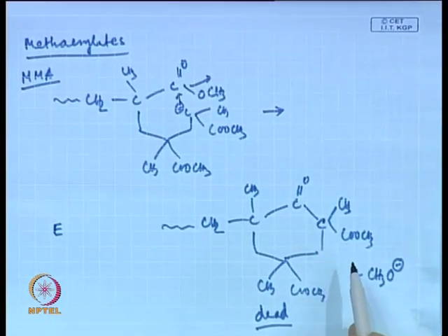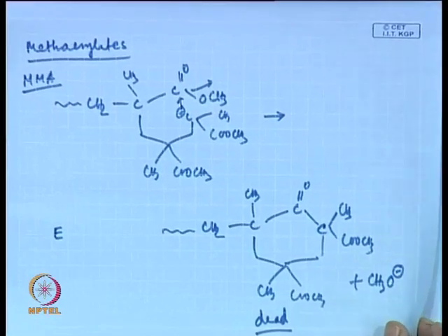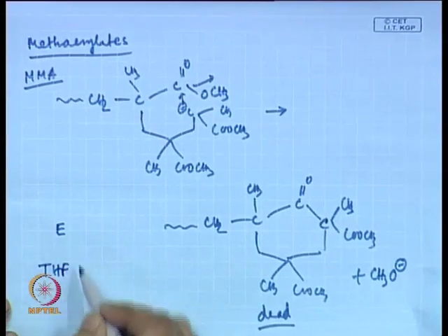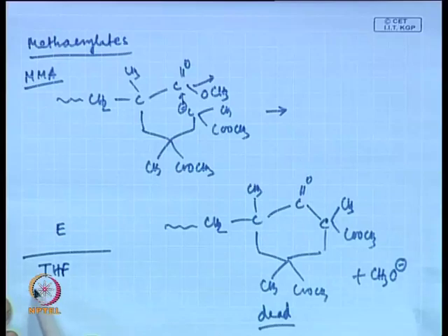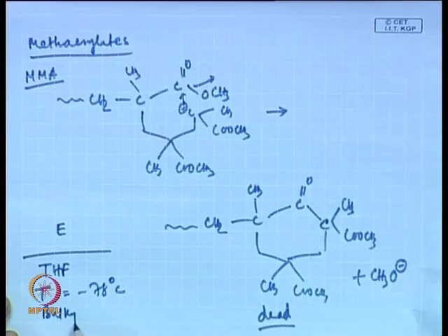Another way to minimize this sort of side reaction is to use slightly polar solvents like THF. In that case you get solvent separated anionic initiator molecules. So, you can actually combine these three strategies: using polar solvents like THF, doing the reaction at a much lower temperature, say like at -78 degrees centigrade, and using a bulky initiator.